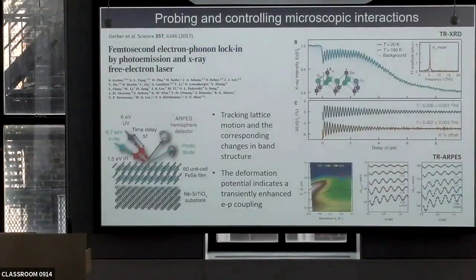One more experiment, which is very interesting, is again from ZX's group. This is a combination now. Here is a little cartoon of two techniques, not done on the same samples, not at the same time. One uses a free electron laser generating almost 9 kiloelectron volt X-rays in a pulse, which you can send onto a sample together with a pump, which excites the sample. You can then follow a Bragg peak in the X-ray intensity as a function of delay between the two, and you're going to see oscillations in that Bragg peak.